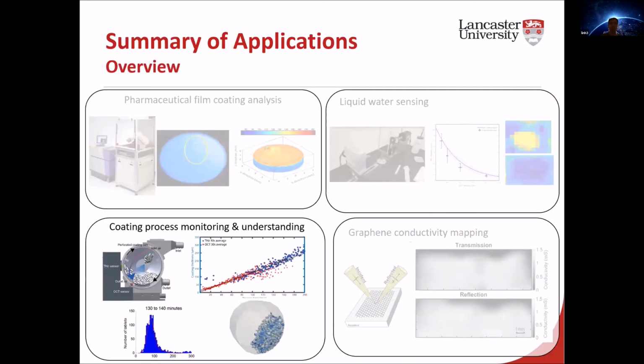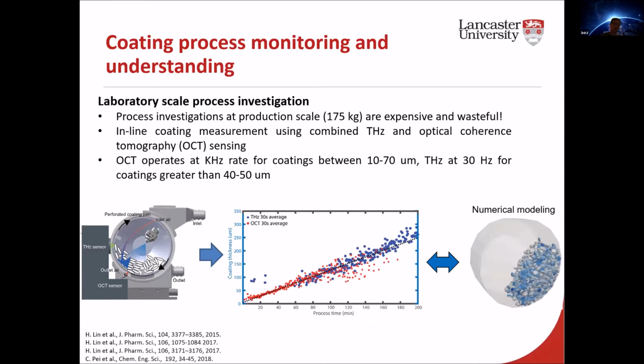So it's very good that we can image individual tablets, but what's more important for the pharmaceutical manufacturing industry is the process monitoring and the eventual process understanding. So the bulk of that work here is really trying to scale down the coating process to a lab-based environment so that we can start collectively studying it with the terahertz sensor. And then here we are also combining with some optical sensor. The reason for combining it is because we can then start looking at very thin coatings. What we want to do there is to combine these different measurements into a numerical process model that is very much designed to capture the process complexities. So this is still very much a work in progress.